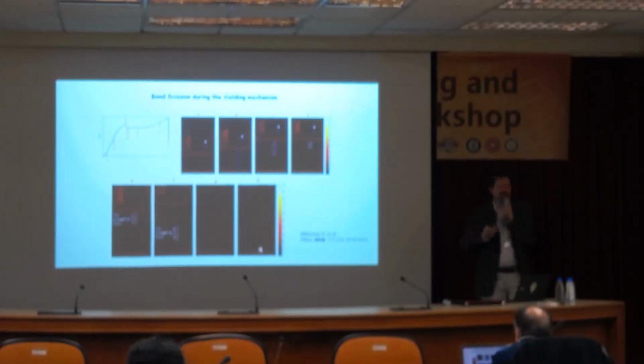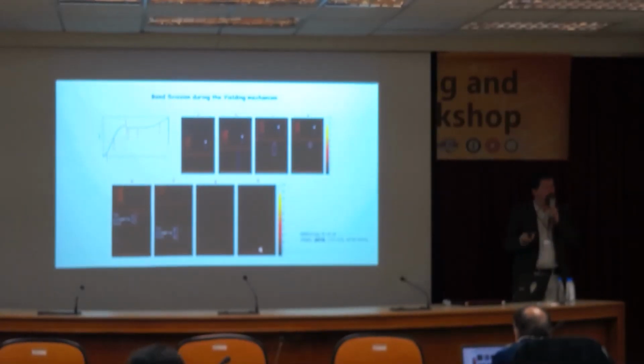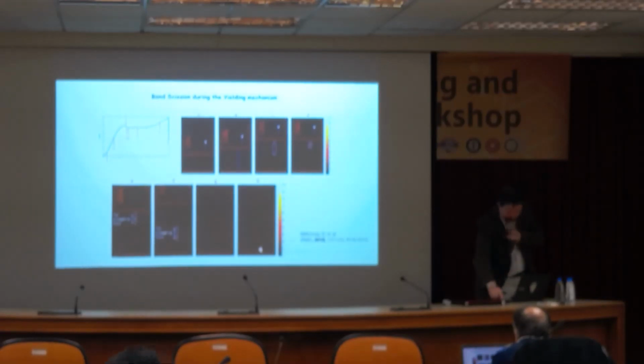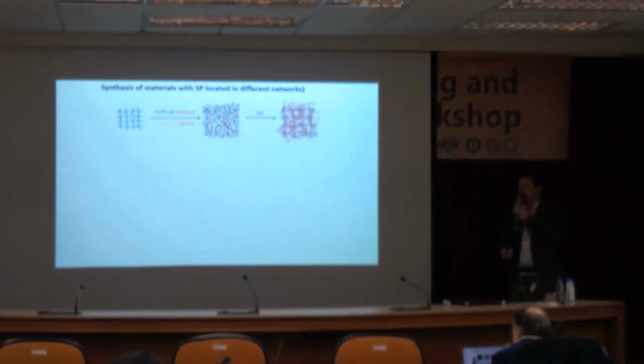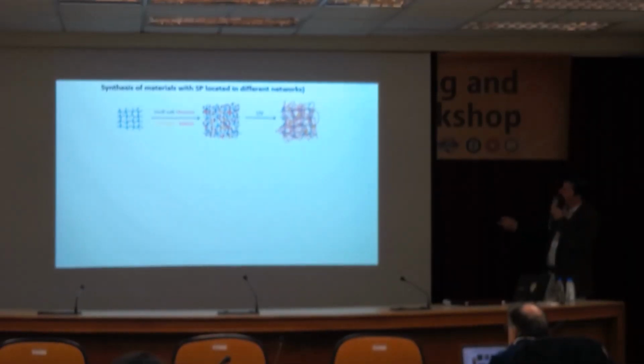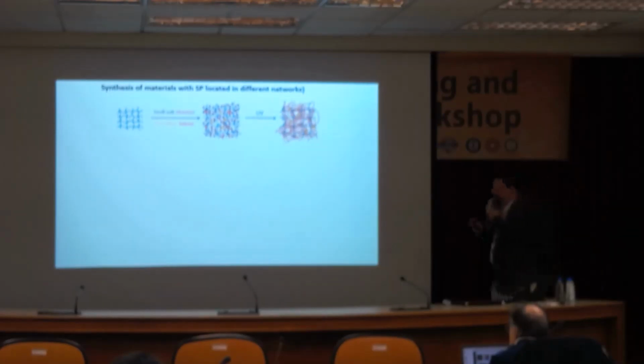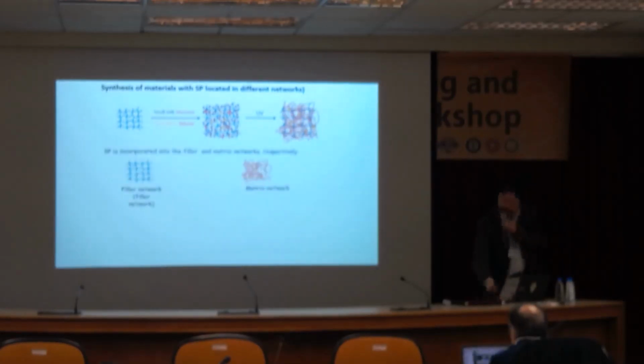So this tells us that indeed there is bond breakage, so it looks consistent with the hypothesis, but that's not really enough. An additional way to look at it is to measure the stress before and after we have this damage. So in this case, this is the network. We can introduce our marker molecule in the blue network or in the red. We can also put it in the matrix to see how the stress is transferred from the filler network to the matrix network. So this is what Yinjun did.